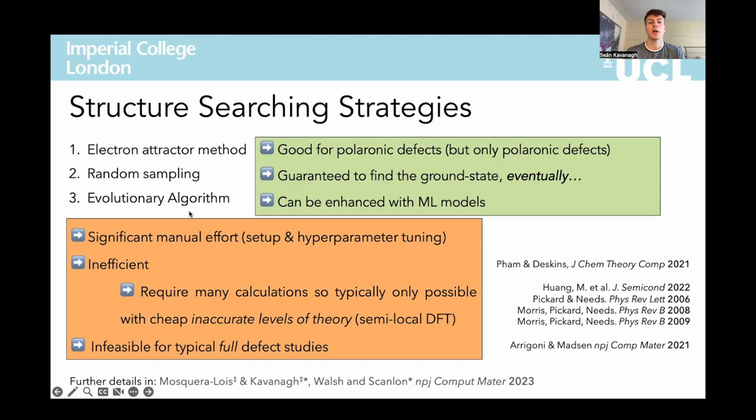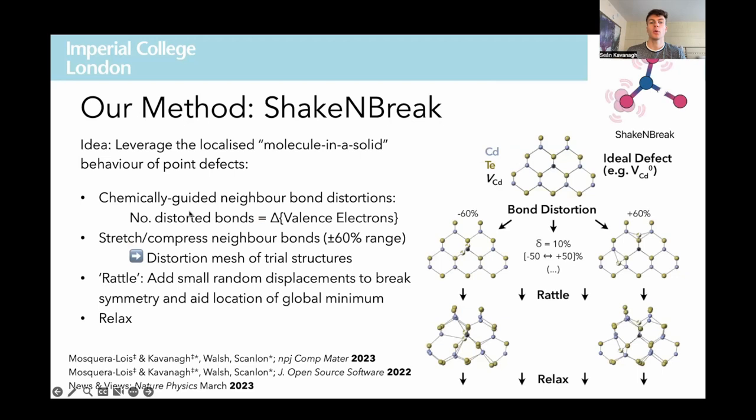With that in mind, we had the goal of developing a method that was both accurate and efficient in navigating the defect configurational landscape and identifying the ground-state structure. The idea was to leverage the localised, molecule-in-a-solid type behaviour of point defects — with dominant interactions with the nearest and next nearest neighbours — as well as the fact that defect reconstructions are typically driven by the need to accommodate the excess charge introduced by that defect species.